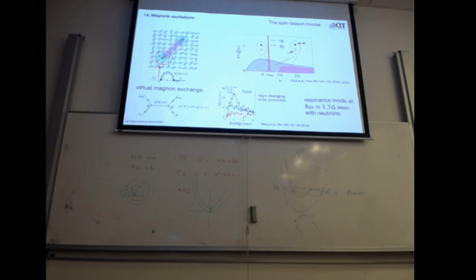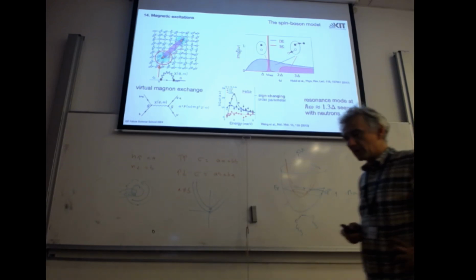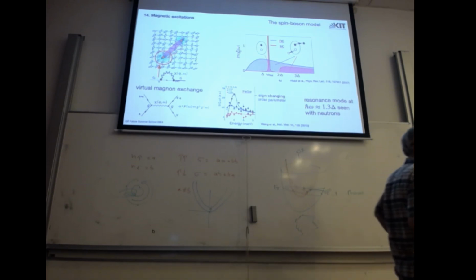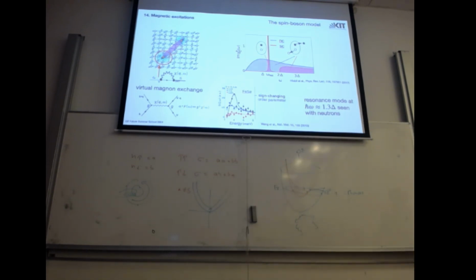Yeah. Sorry, antiferromagnetic stability comes somehow as a surprise. You somehow highlight why. So why look at cuprates? Cuprates are superconductors, but the parent phase is an antiferromagnet. Or if you look at nickelates, you can do neutron diffraction and neutron scattering, and in neutron scattering you see you're close to an antiferromagnetic phase, but they are not antiferromagnets.